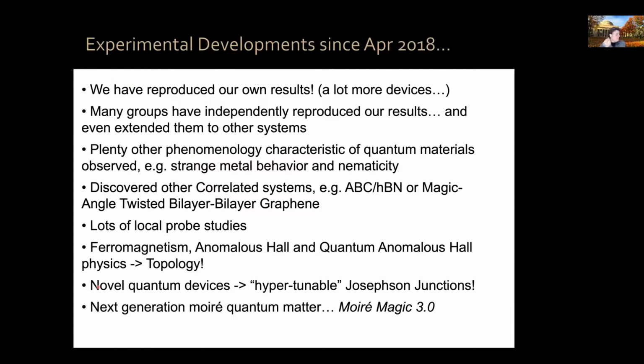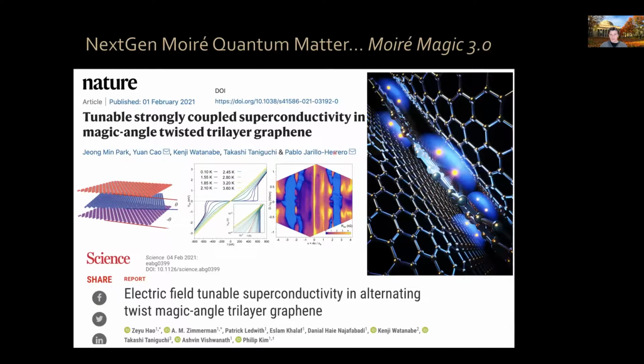Now, the next thing that I want to tell you is that we have realized the next generation of moiré quantum matter, okay? Based not on bilayers, but on multi-layers. I call this moiré magic 3.0. So earlier this year, the group of Philip Kim and my group too, we reported back-to-back in Science and Nature the discovery of a second moiré superconductor, okay? It is magic angle twisted tri-layer graphene, now 3 layers twisted on top of each other, okay? So it's quite interesting. It's an even more tunable superconductor than magic angle bilayer graphene, because now we can tune it also with a transverse electric field, and it realizes a strong coupling limit of superconductivity, okay?